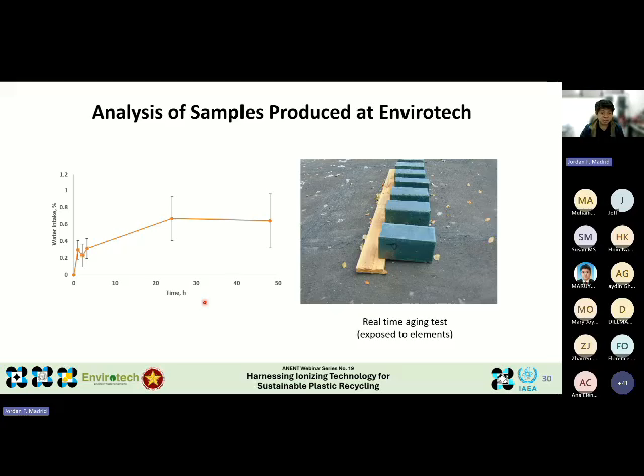In addition, we carried out real-time aging tests. The samples we prepared last February 2025 were brought back here to PNRI and directly exposed to natural outdoor conditions - sunlight, rain, and even stormy conditions - from February to July 2025, covering a span of more than 5 months. This kind of exposure test is valuable because it simulates the actual stresses and weathering that the materials will encounter in real application.